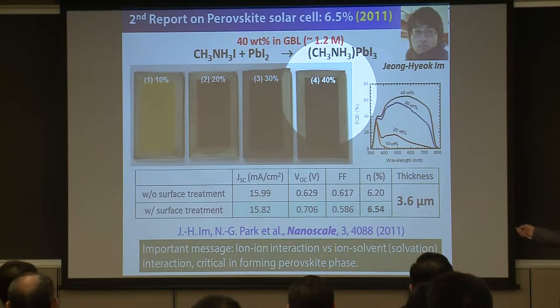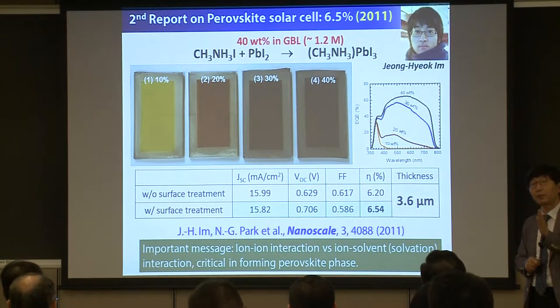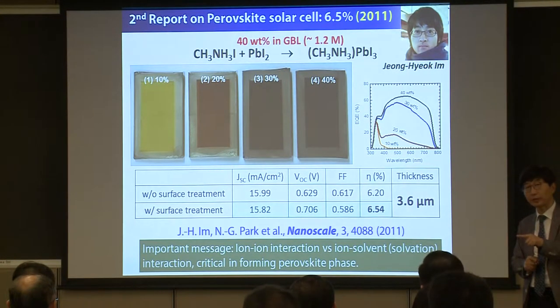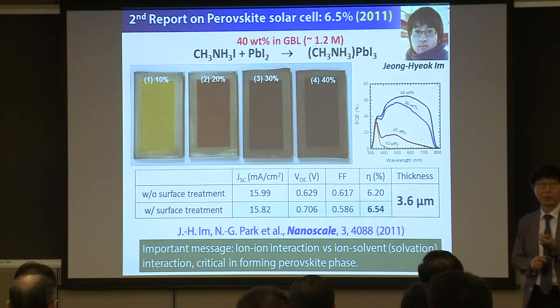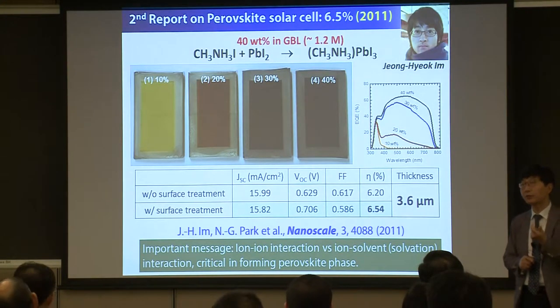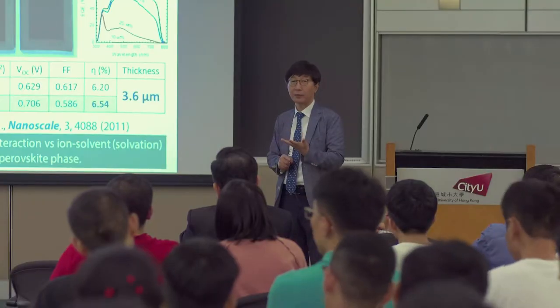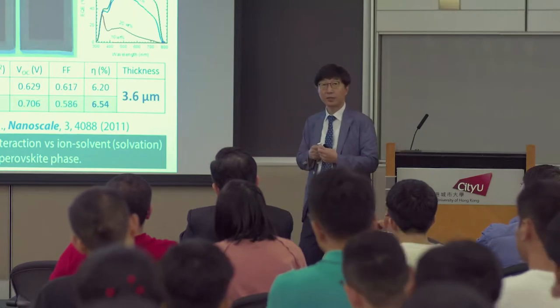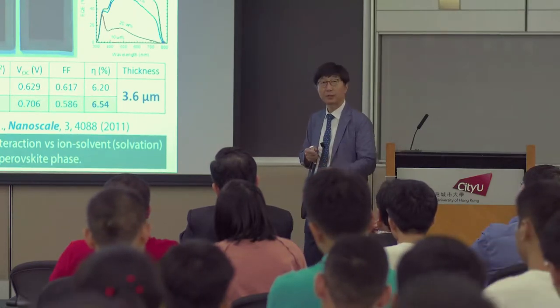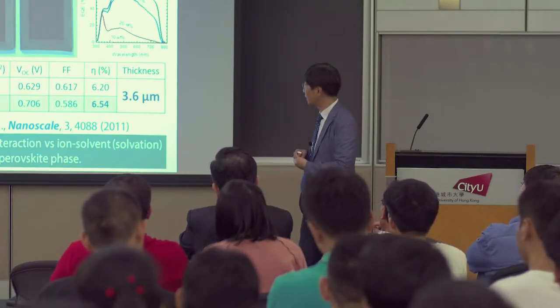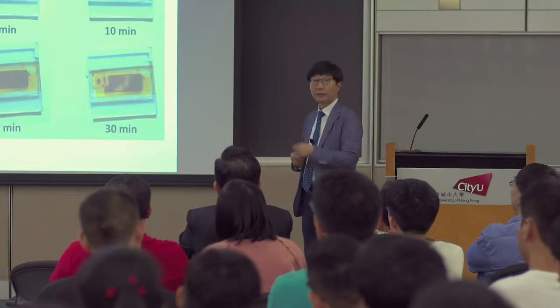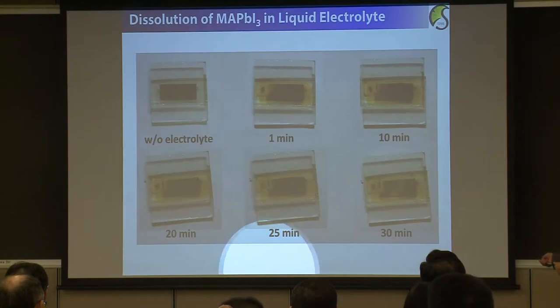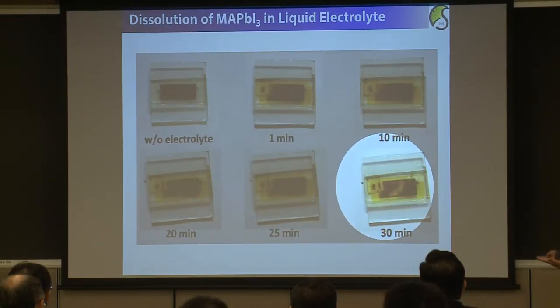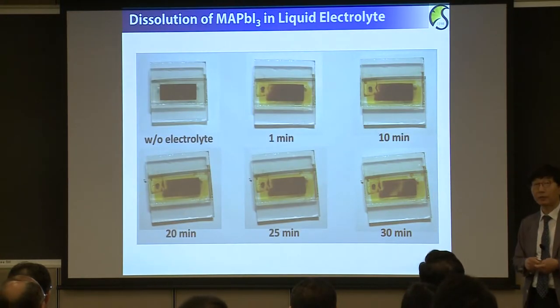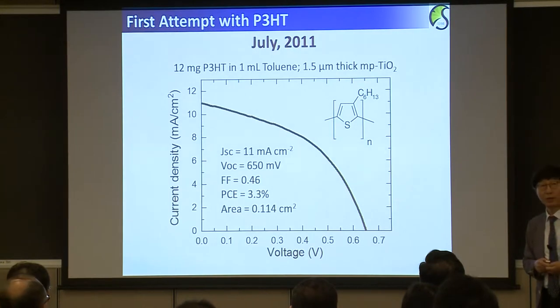The high concentration. Why is high concentration important in the coating solution? Because you have to think about there being so many ions in the coating solution. So ion-ion interaction and ion-solvent interaction will compete with each other. Then, if you increase the ion-solvent interaction, you may not have the perovskite phase. So increasing the concentration will increase the ion-ion interaction. You can eliminate the ion-solvent interaction. But as I mentioned, this material is unstable in the presence of a liquid electrolyte. So I would like to replace this liquid electrolyte with a solid hole conducting material.